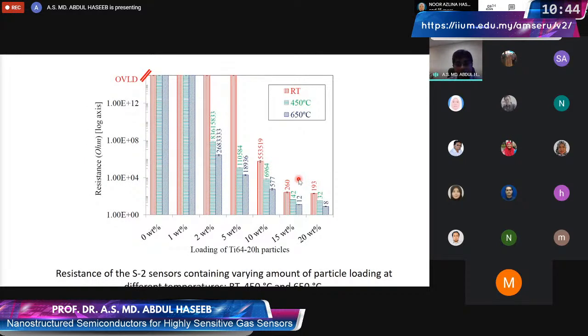And this is the result of the resistance measurement on this nanowire in ambient. And as you can see, when the particle loading is less than 1 weight percent, then we have very large resistance, and we cannot measure anything.